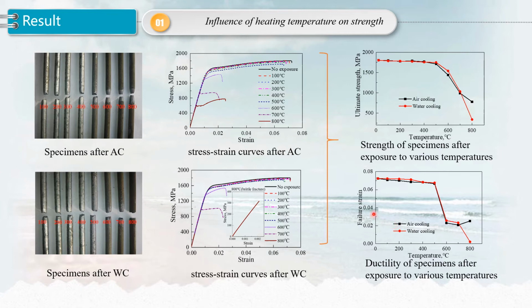Above 500 degrees centigrade, the strength of specimen began to decrease rapidly with increasing temperature, together with a dramatic reduction in final strain in the same temperature range. Comparing the two kinds of cooling method, nearly no apparent difference was observed below 700 degrees centigrade. When the heating temperature reached 800 degrees centigrade, there was nearly no strain in the water cooling specimen at failure, and the specimen failed in a purely brittle manner.